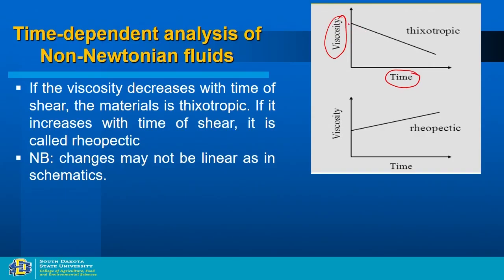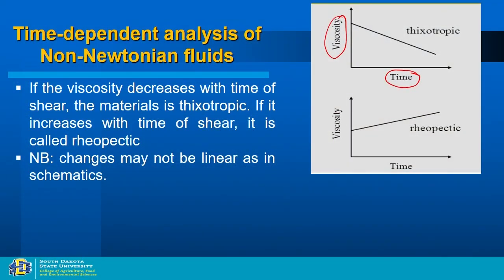So basically, the way they measure these things is, you have the fluid, whatever you want to test the viscosity, test their time dependent behavior. So you have the fluid, you put it in some type of viscometer, and then you shear the sample at a constant shear rate. Then you monitor the shear stress with respect to time. So shear stress over shear rate gives you viscosity. So you are plotting the viscosity with respect to time. So it is not the yield stress at all. It is just viscosity at 0 point, and then follow the behavior.